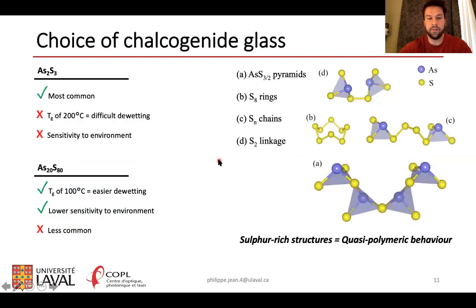So the choice of chalcogenide for the study of dewetting is actually very important. In this work, we studied two different compositions. The first one was As2S3, which is the most common chalcogenide glass, and there's a lot of data available in the literature on its properties. But it has a relatively high Tg of 200 degrees Celsius, which makes it a bit more difficult to study dewetting. So the second glass we used was As20S80, which is a lot less well known. So there's less data available in the literature, but its Tg is much lower at 100 degrees C. So it makes it much easier to study dewetting inside this glass.